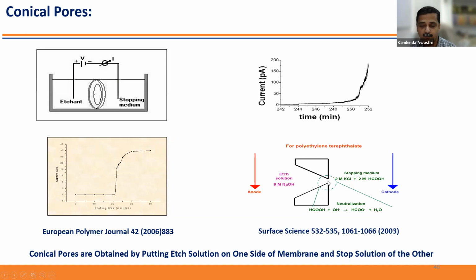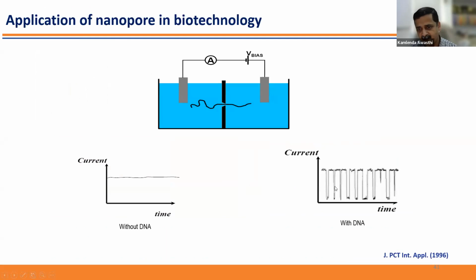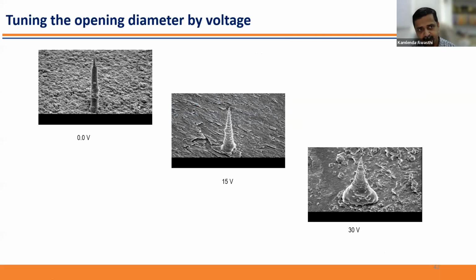So this is a very small opening. On the left-hand side, the opening is a few microns, but on the other side it is a few nanometers. And this has applications in biotechnology, detection of biomolecules without any chemical or other treatment. So this is the current signal without DNA. And once the DNA passes through this conical membrane, you can see this blockage, and this is the current dwell time. By calculating this time, you can calculate the length of your DNA molecule.